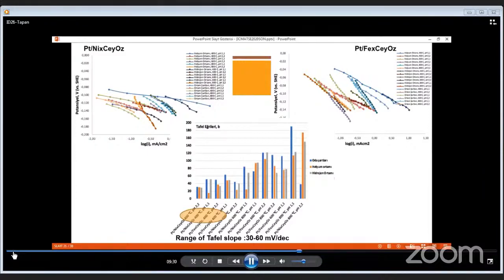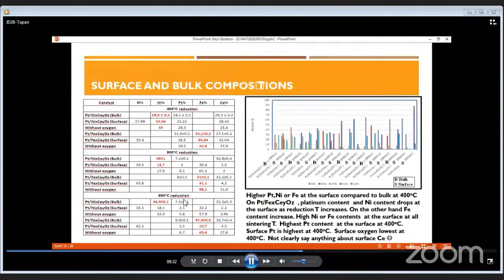After determination of surface and bulk composition by XPS and ICP techniques, we have seen that there is higher platinum, nickel, or iron at the surface compared to bulk at 400 degrees. On platinum, iron, cerium catalysts, platinum content and nickel content drops at the surface as reduction temperature increases. Unlike iron, the highest platinum content at the surface was observed at 400 degrees. In addition, on the catalyst surface, oxygen was lowest at 400 degrees also.